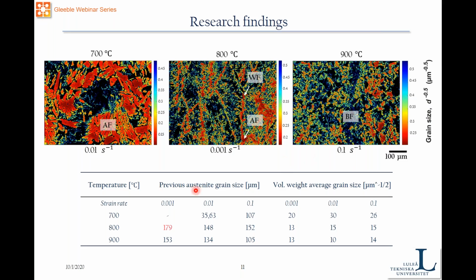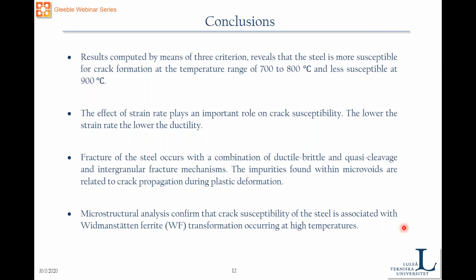It is also why I measured the previous austenite grain size. It's because previous studies have demonstrated that Widmanstatten ferrite can be promoted if the previous austenite grain size is large, and it is promoted by the deformation and also by the grain size of austenite. So what we concluded in this work is that these three criteria give us more or less where the material is susceptible to crack formation, that is between 700 and 800 degrees, and less susceptible at 900 degrees. So the effect of the strain rate also plays an important role, as I mentioned before. The lower the strain rate, the lower the ductility. So if the company decides to increase the casting speed, it will be beneficial for the material as well.